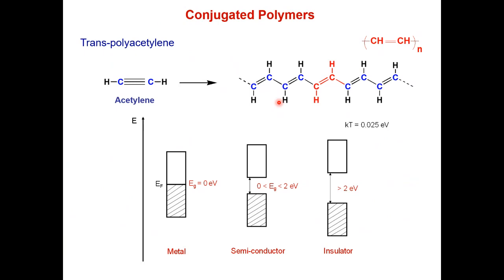It will be very, very difficult, because I guess that with a conjugated polymer, your HOMO is around 5 eV. With a standard polymer like polyethylene, like I guess many biopolymers, the HOMO is at minus 10 eV. And so it's very difficult with a metallic electrode to go and remove electrons 10 eV below the vacuum level. So I think it's difficult.